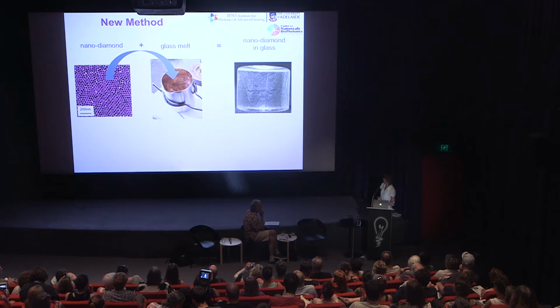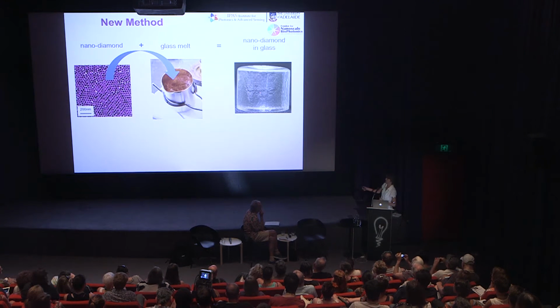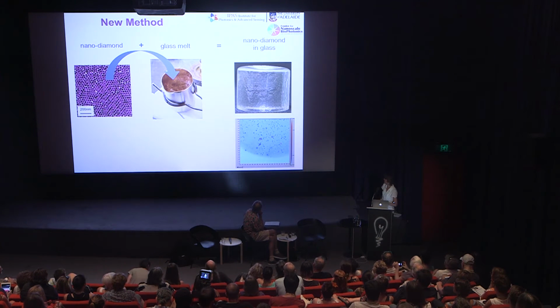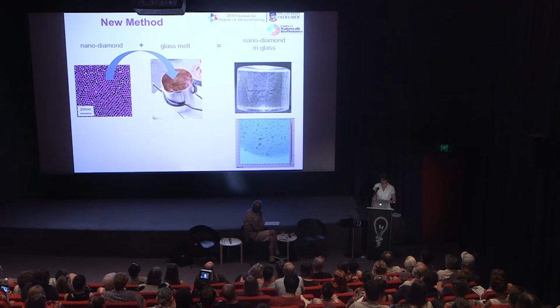And the billet you see here is relatively clear because we only put in a little bit of nanodiamond. And this was also 3 years' work to make it look transparent. I come to this more in the next slide. But here you can see a confocal microscope image showing all the nanocrystals, which show a very particular fluorescence. And so they are lit up under the confocal microscope.